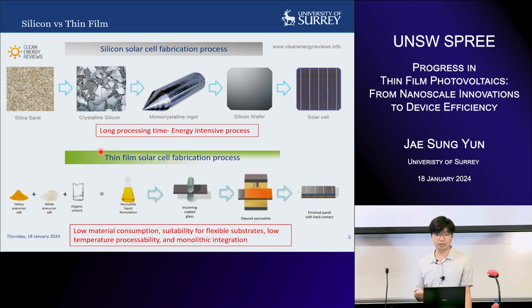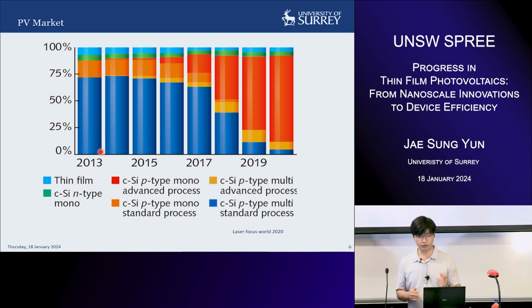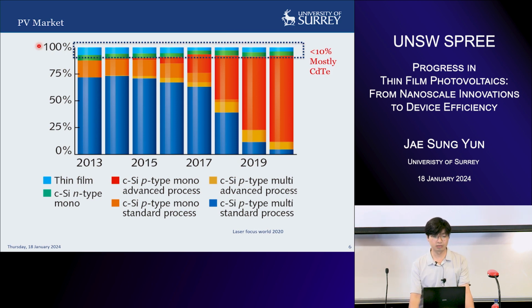I think many are familiar with the silicon solar cell process. Fabricating the wafer is an energy intensive process, which has good efficiency and good stability, and currently dominates the market. Whereas for thin film solar cells, the fabrication process is known to be much more straightforward, with low material consumption. It can be deposited onto a flexible substrate, there is low temperature processability, and we can make very large monolithic integration devices. So those are the advantages of thin film. However, wafer-based solar cells have more than 90% of the market, whereas the thin film market share is gradually reducing, to less than 10% in the current market. Most of it is cadmium telluride manufactured at First Solar.